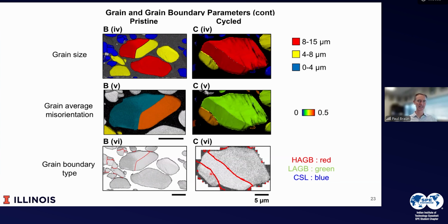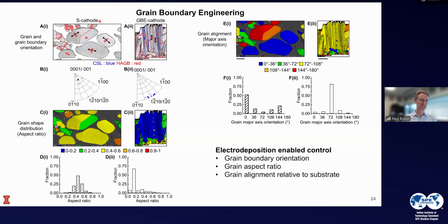And if we look at that, you can look at grain size, and so in fact we see that there are size effects to the cracking, and most important, we can map out the grain boundary types, and the cracking here is occurring along a high-angle grain boundary. High-angle grain boundaries have the lowest cohesion energy and thus are the most susceptible to cracking. The difference is that if I make powders, I can't control it. When I do the electrodeposition, I can engineer all of the grain boundaries. And because I can engineer it, what I will show you is I can control the mechanics, which means I can control the cracking. And so this is another advantage of growing the electrodes via an electrochemical approach versus the randomly oriented material.